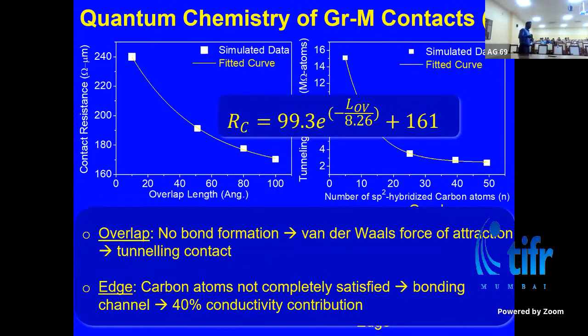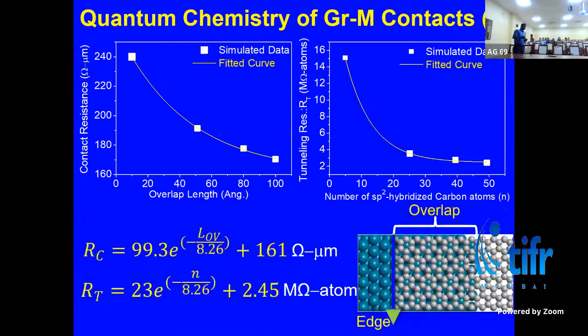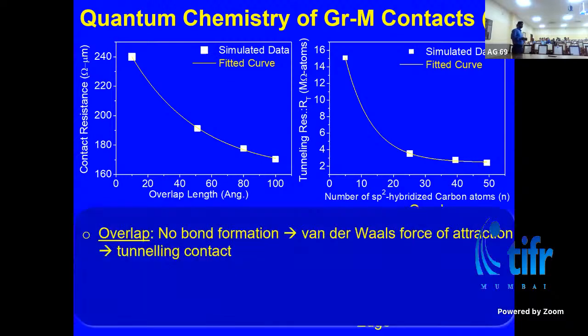And the other one, on the edges, the carbon atom is not completely satisfied. So we have a bonding channel, and that bonding channel results in 40% of the electron contribution. If I go back and keep increasing the overlap length and force the system to behave more like a Schottky interface, I mean, if the edge is too far from the channel, this system will be dominated by the overlap region, right? So if I keep increasing this, it saturates to this 160 ohm micrometer, which was also theoretically predicted earlier as the quantum dimension, right?